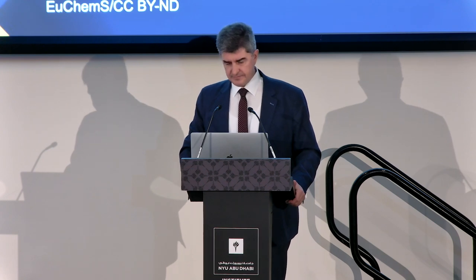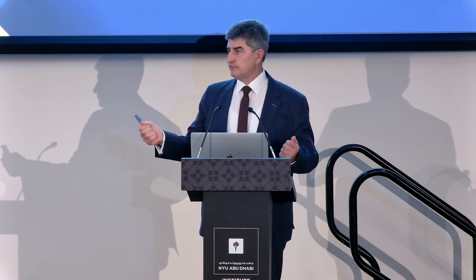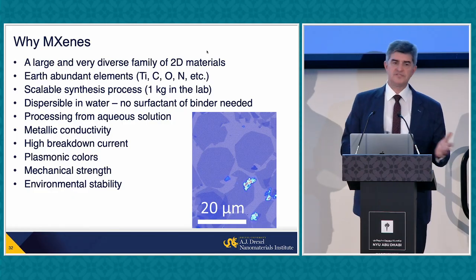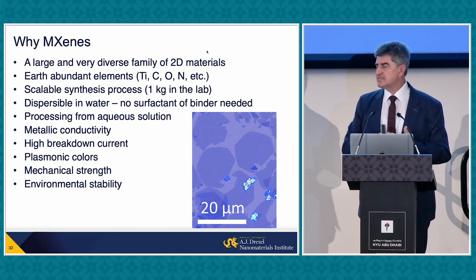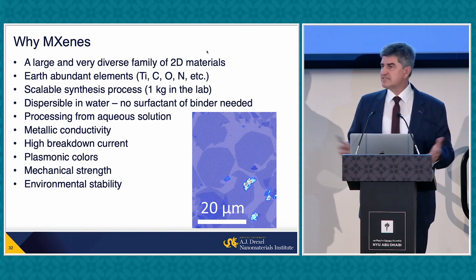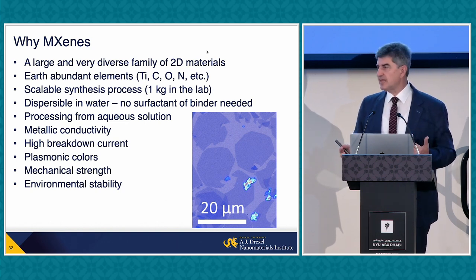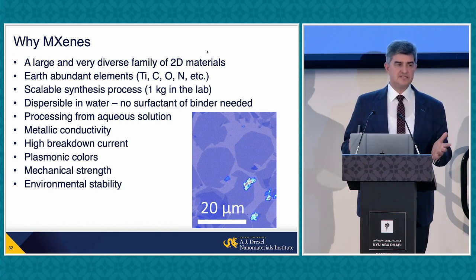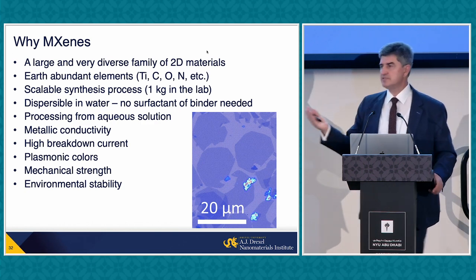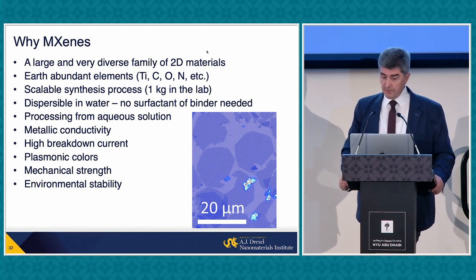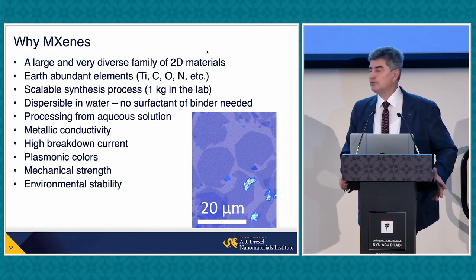It is possible. But there are two things. One, the same surface charges and strong interactions that I mentioned prevent MXene from restacking, form strong films right away after drying, and make it more difficult to peel it off. But you can do it. You can mechanically exfoliate by, for example, milling, or we use a three-roll mill. We published a paper recently. You can separate MXene without intercalation, or mix them with polymer material and separate at the same time. And it has also been shown that even from MAX phase, it's still possible to mechanically separate sheets. You cannot easily make single layer sheets. So it is possible, but it doesn't seem to be an optimal way to do it.